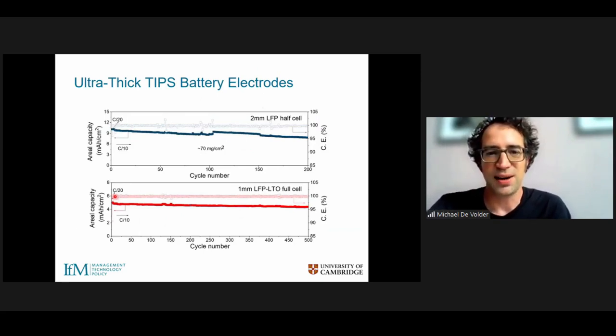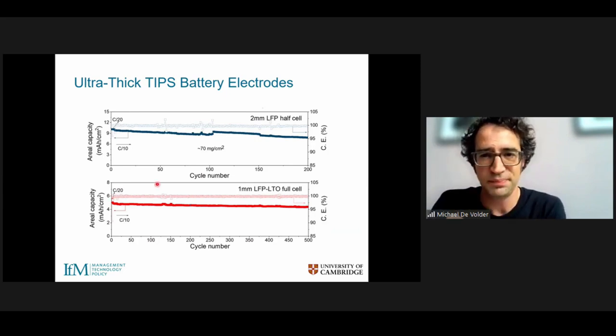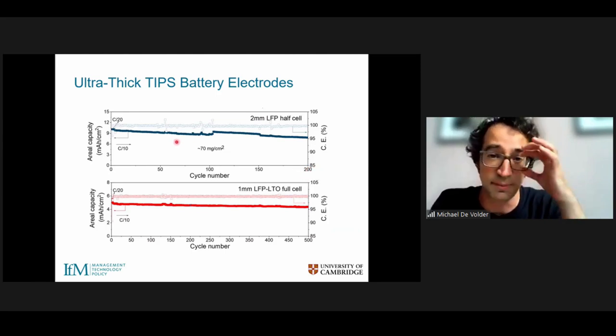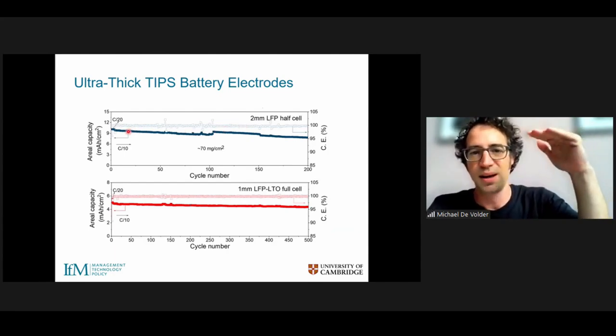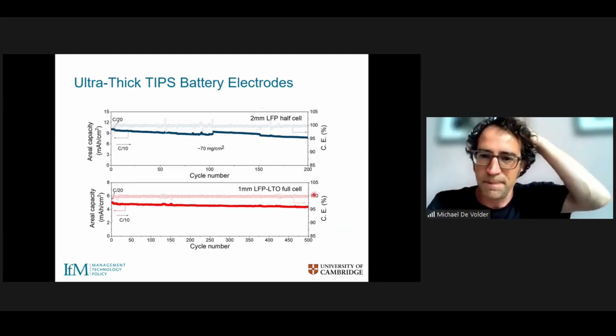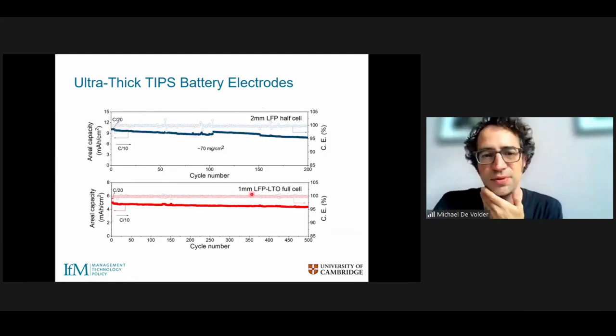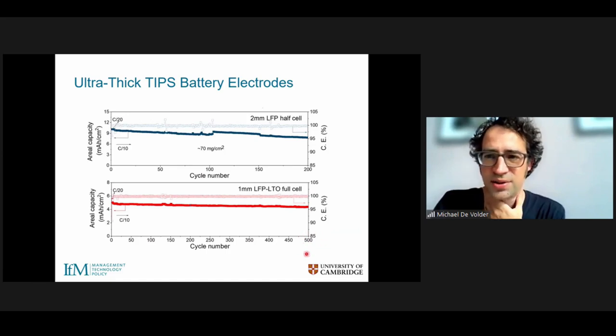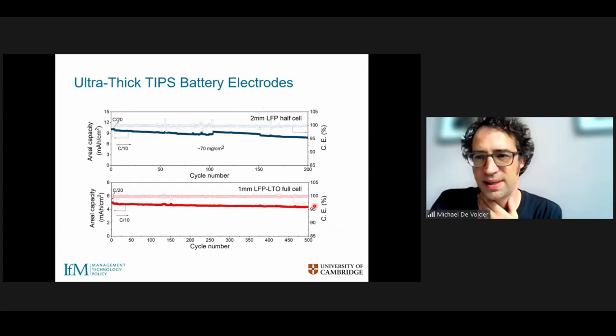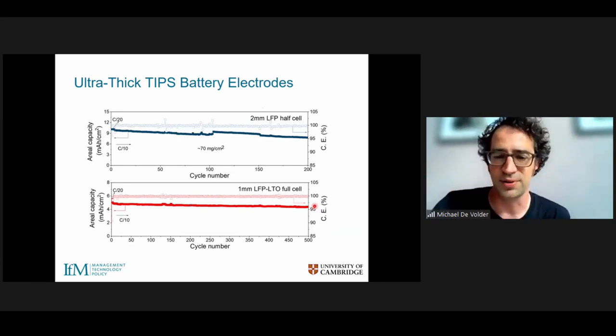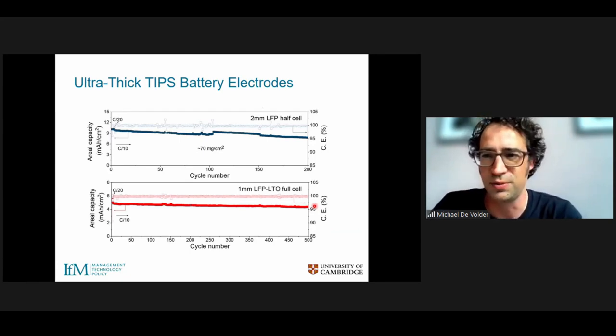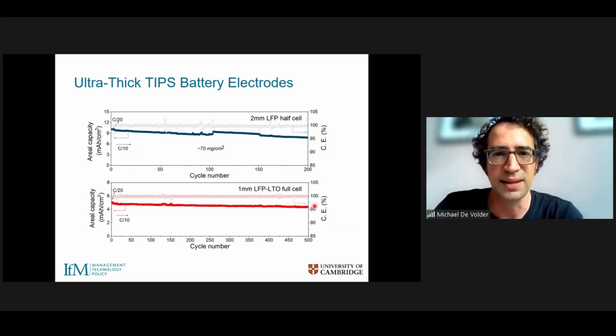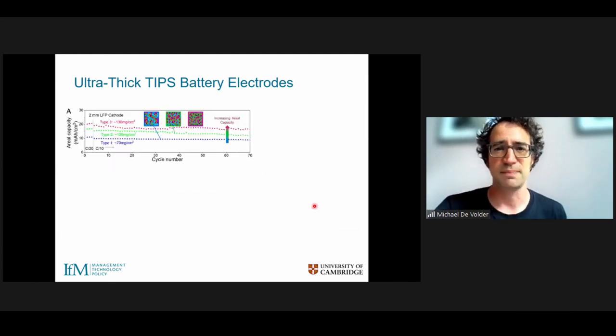It's also quite important to check how these batteries behave over long-term charging and discharging. What we are looking at here, at the top, is a 2 millimeter thick electrode, which we charged and discharged 200 times in this case, and there was a little glitch in the middle here. But other than that, you can see a fairly slow but constant decay in capacity. And at the bottom, we've done the same, but using 1 millimeter thick electrodes. Over 500 charges and discharges, we've retained about 87% of our capacity. So there's a very reasonable amount of capacity fade, despite using these very thick electrodes, which is unusual. Normally, thick electrodes tend to lose their capacity very rapidly. And that's a nice aspect of these TIPS processes.